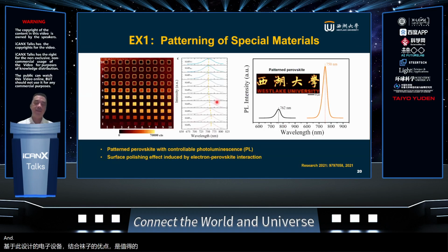Another case of special materials is perovskite, because we all know that perovskite is very sensitive to the e-beam. So you can use the e-beam to pattern the structures because they will have different photoluminescence. Then we can again combine e-beam lithography together with ice lithography, and carefully control the photoluminescence, PL, of such devices. The first paper came out last year, and we will have another paper coming out on how to make a very easy perovskite electronic device based on this. For the details, probably that will be another talk.